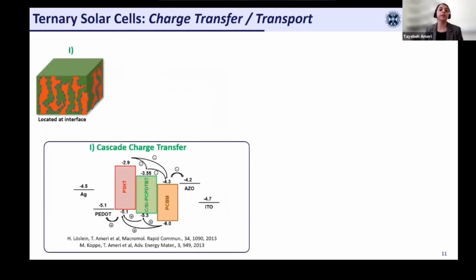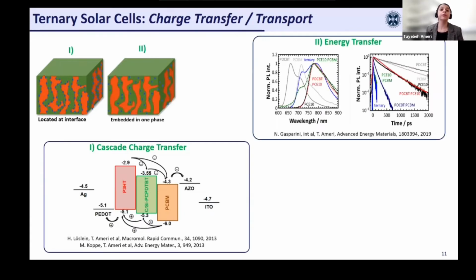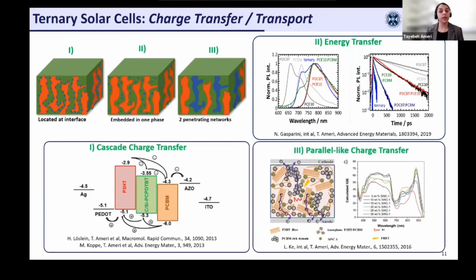One of the first mechanisms that we revealed was cascade charge transfer, where the energy level of our sensitizer is sitting between the energy levels of our host donor and acceptor. And in this way, the produced charge carriers can have a cascade charge transfer. It's actually corresponding mainly to the morphology where the sensitizer is sitting at the interface of our host donor and acceptor. If the sensitizer is embedded in one of our host phases or well intermixed with one of our host materials, then energy transfer is the most corresponding mechanism. And if the sensitizer is on its own good enough in packing and transport properties, then it can form its own penetrating network and have a direct contribution in the charge transport, which is also called parallel-like charge transfer.